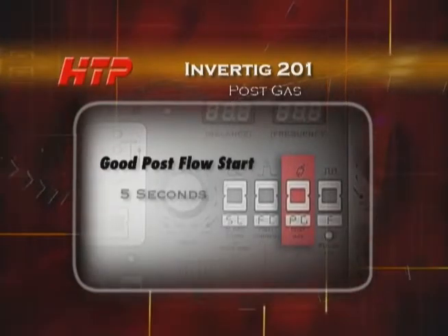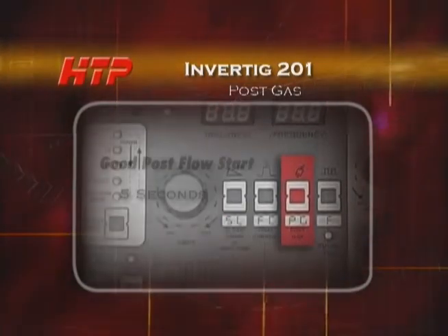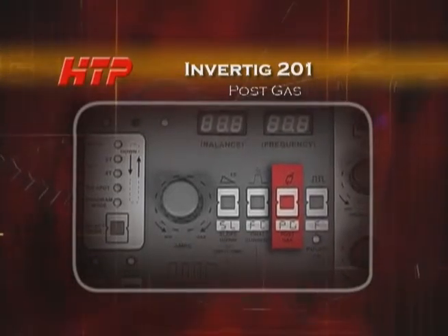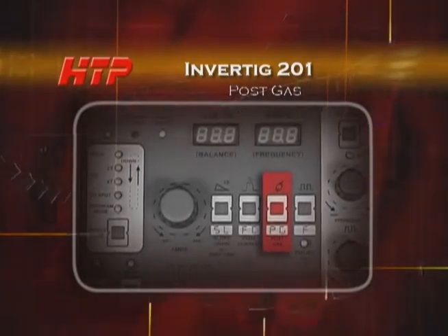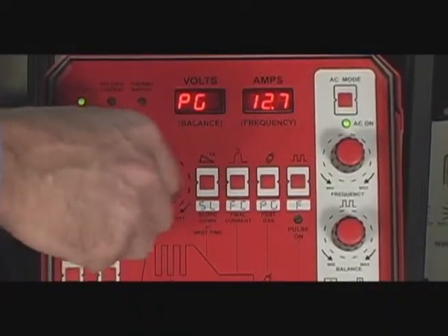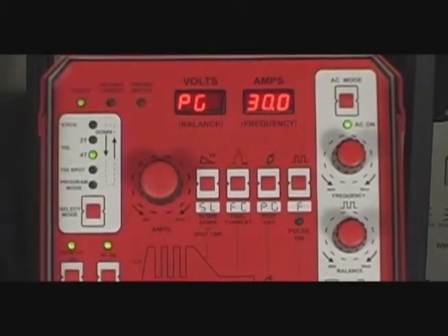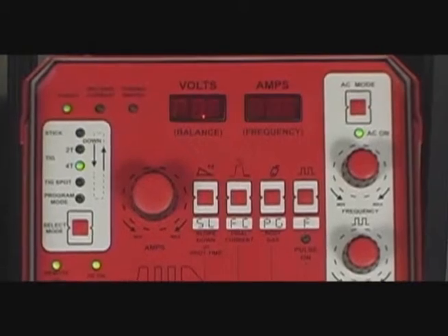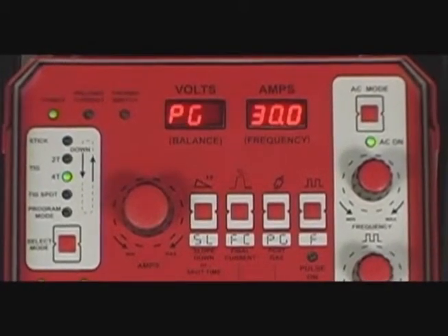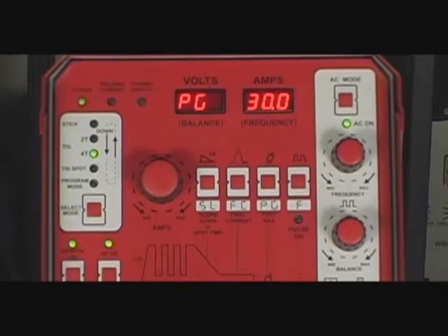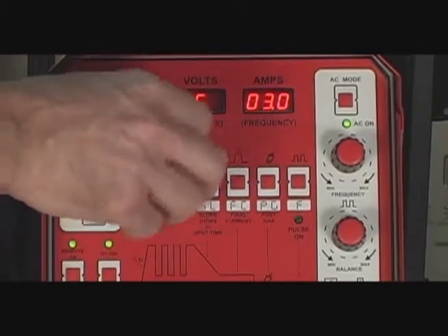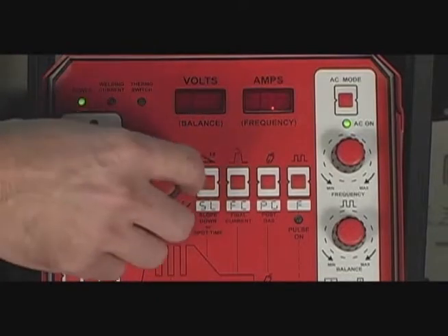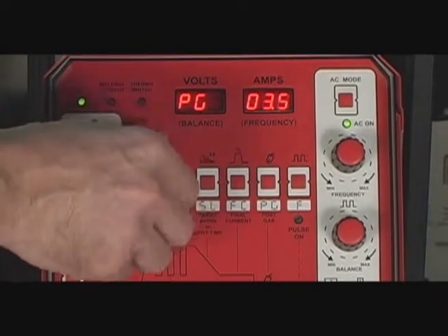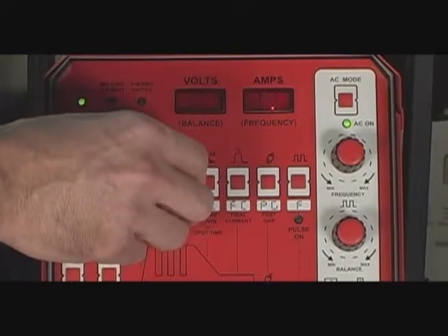A good starting point for the post-gas flow is 5 seconds. If you are welding at higher amperages or on more critical alloys, it may be necessary to increase the post-gas flow to a higher value. To adjust the post-gas time, depress and release the post-gas button. The volts display will flash PG for post-gas, and the amps display will flash and display the post-gas time in seconds. While both displays are flashing, adjust the amps knob to set the post-gas flow time in seconds. The post-gas flow is adjustable from a half a second to 30 seconds in 1/10 of a second increments.